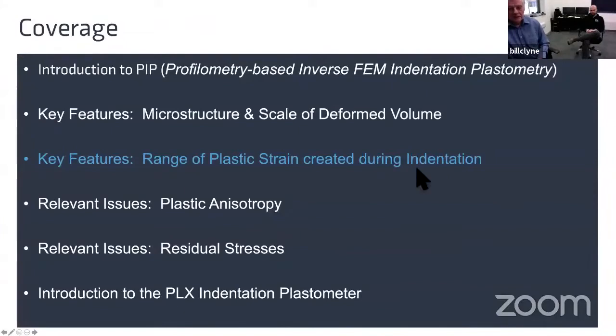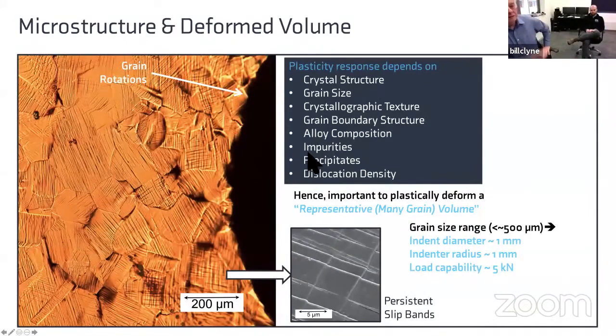And this is an important issue. What scale should you do this on? If you make very small indents, you'll probably be in single grains and you'll get very different behavior. Because if you want to capture the bulk response of the material, you do need to deform a relatively large assembly of grains, what you might call a many grain volume.